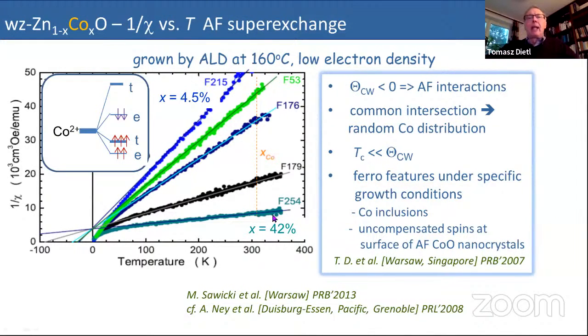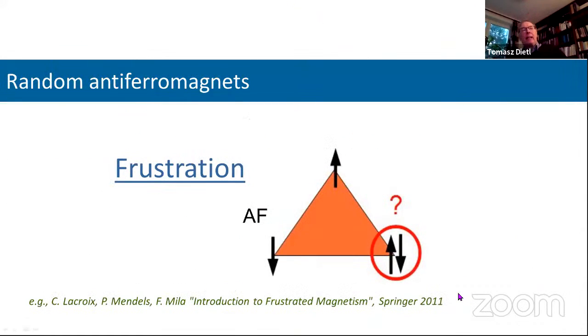And to give you an idea about the energy involved, theta, the Curie-Weiss temperature extrapolated to 100% of cobalt, is of the order of 700 K. So it's a large energy, and actually this large energy of interaction means that at room temperature we still have uncompensated spins at the surface, which are ordered by antiferromagnetic interactions surviving up to room temperature.